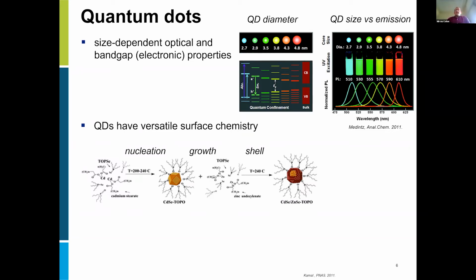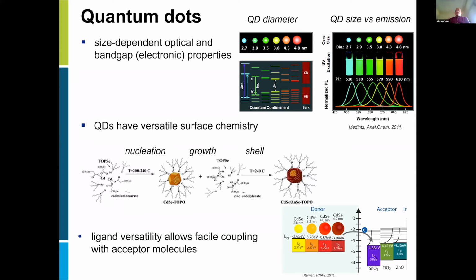Like I mentioned before, quantum dots can absorb light, harvest the light, and create these quasi-particles, excitons or electron-hole pairs. So the mission here is to extract electrons and holes out of these cores and to create things like solar cells. In doing this, the chemistry that we can do at the outside of the quantum dot allows us to connect to a variety of acceptor materials. And here is an example where we have a series of quantum dots of different size connected with, for example, oxides, which are known as good electron acceptors.